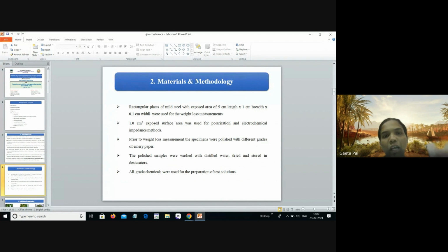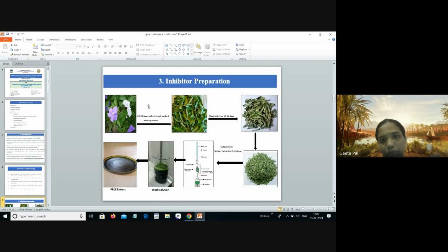Materials and methodology: a rectangular mild steel plate with an exposed surface area of 5 cm length, 1 cm breadth and 0.1 cm width was used for weight loss measurement. A 1 cm square surface area was used for the electrochemical measurements. All the metal samples were polished with different grades of emery papers. Then they were washed with acetone, then washed with distilled water, dried and stored in a desiccator. All AR grade chemicals were used for the test solution.